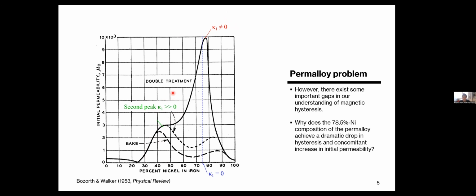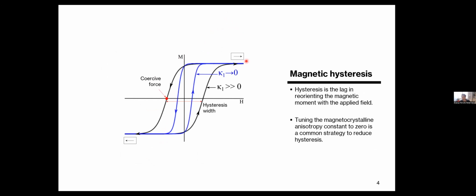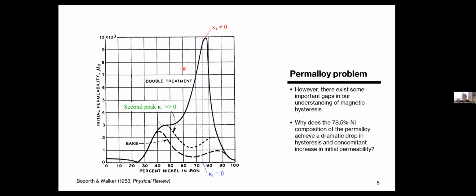So it goes back to us questioning whether the idea of just tuning the anisotropy constant close to zero is the only way, or the primary or dominant factor that's controlling the width of your hysteresis loop. This is an example of an outlier which shows there are some gaps in our understanding of how we think of magnetic hysteresis, and whether this constant plays the primary role.